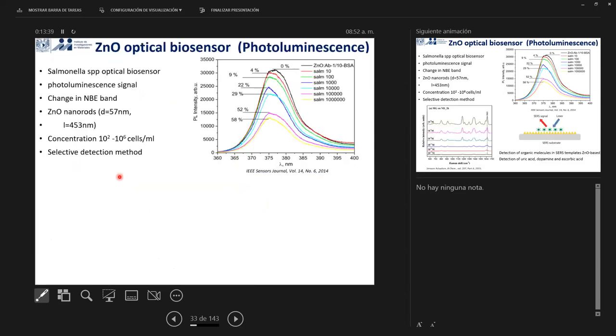There are some reports earlier where people have used zinc oxide optical biosensors for the detection of Salmonella and some other pathogens, for example. And what they have done is they have grown nanorods of diameter around 57 nanometers, length around 400, 500 nanometers, and then they vary the concentration of these analytes. And when they vary the concentration, they have seen that there was some change in the output response of the photoluminescence. In this case, we can see that intensity was changing when they increased the concentration, and also there was